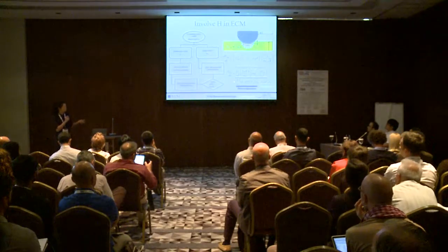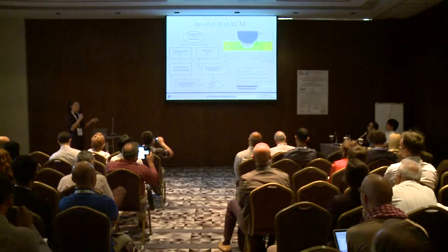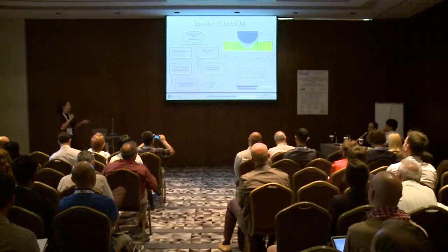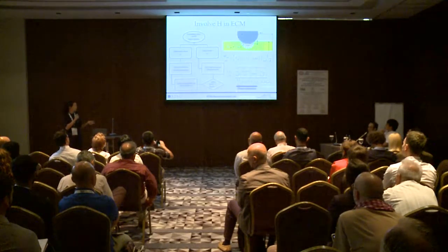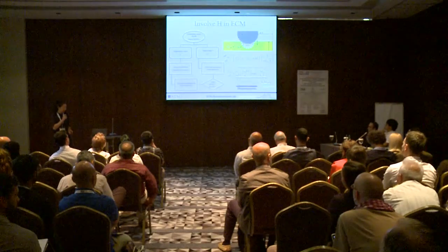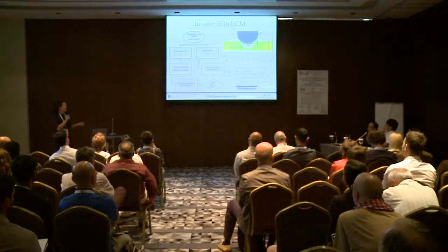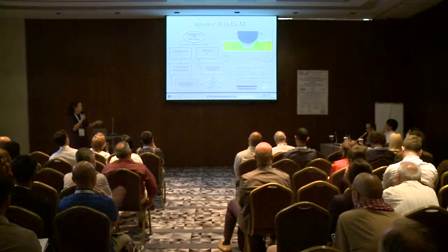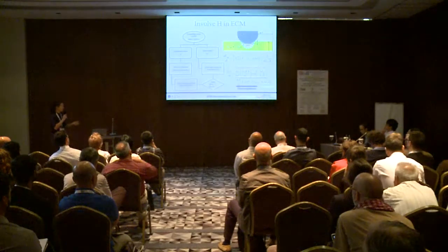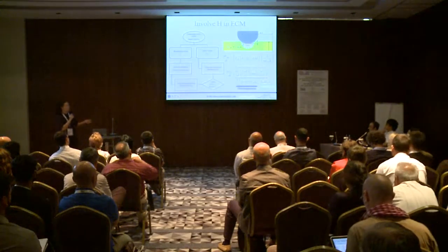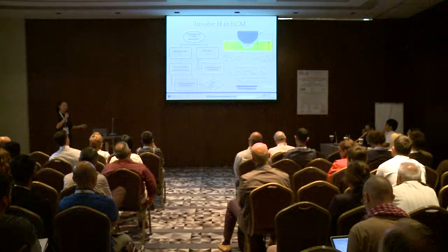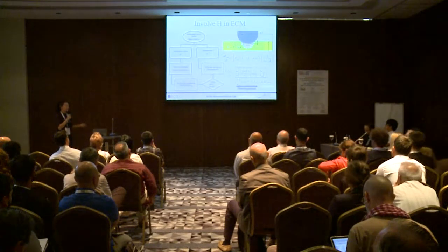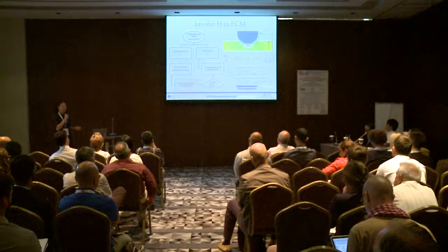Here is some more to emphasize: in this dislocation density evolution, we have three contributions: the homogeneous nucleation of dislocations and the heterogeneous nucleation of dislocations, both of which are well covered in nucleation theory, and the dislocation annihilation contribution. All of them are influenced by hydrogen. When hydrogen enters the plastic zone and is trapped by a dislocation loop, it influences the dislocation energetics and mobility.